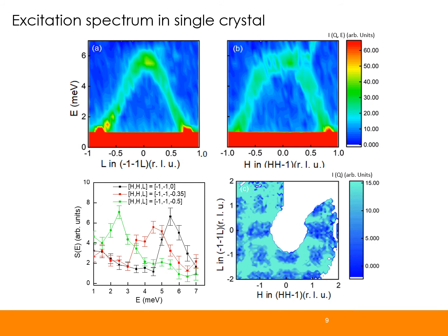These are the spin waves which I measured from the co-aligned single crystals. The first two figures represent the spin wave along the high symmetry directions 001 and 110. The spin wave along the 110 direction shows some sloped feature or asymmetry around the zone boundary. The third figure is the line cuts at different regions in the reciprocal space, and the last figure in the slide is the constant energy cut, and the circular region shows the constant energy portion of the spin wave cone in this material. For this plot, we took the constant energy 3 meV.